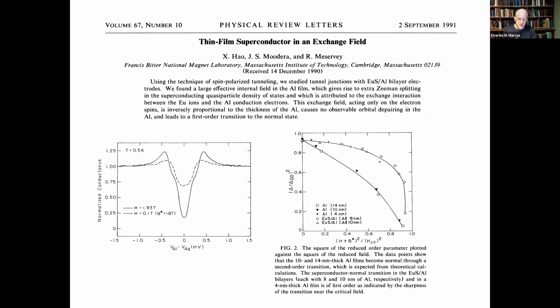These same studies looked at the gap that was induced. And here I want to draw particular attention to the figure caption underneath figure 2, which reads: the square of the reduced order parameter. Reduced order parameter just means that they've divided the gap by the zero field gap. It's 1.76 times the transition temperature, against the square of the reduced field, the field that they've applied in units of the critical magnetic field, so that at 1, the system goes normal.